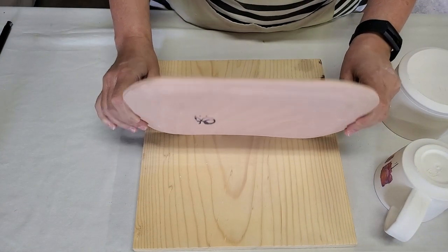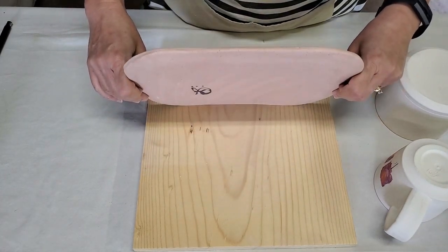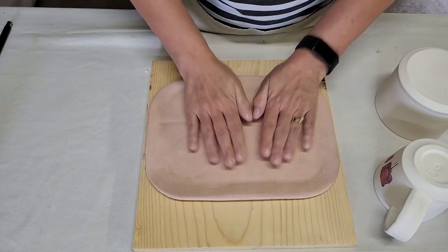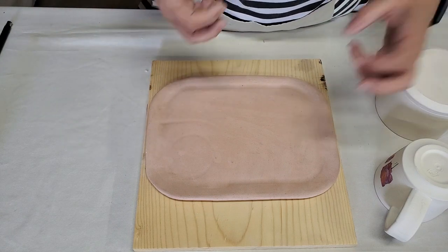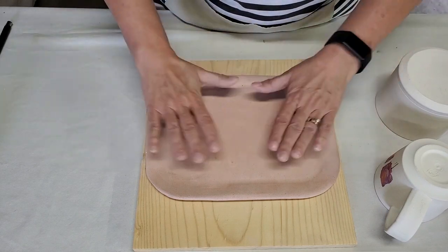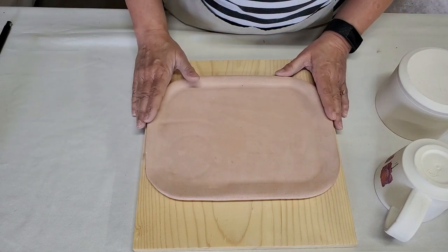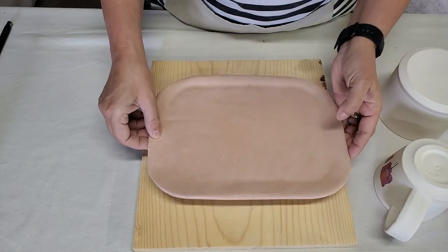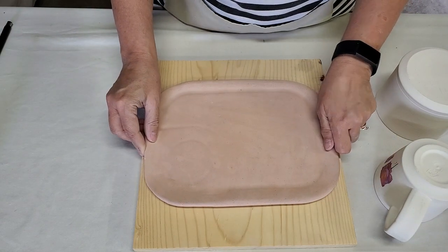The final one is a warped flat piece — you can see it's arced and not flat at all. The way I could have fixed that is to put some weight on top of it while drying — a lot of people use bean bag weights filled with beans, rice, or sand wrapped in an old t-shirt, set right on top. I should have covered it, but I set it out and it has muscle memory, so it decided to give me a little arc. I'm saving this because I want to try some raku firing on it and see what kind of looks I can get.